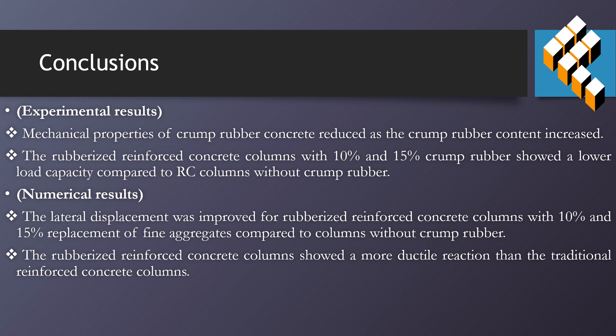Numerical results showed that lateral displacement was improved for rubberized reinforced concrete columns with 10% and 15% replacement of fine aggregate compared to columns without crumb rubber. The rubberized reinforced concrete column showed a more ductile reaction than the traditional reinforced concrete column.